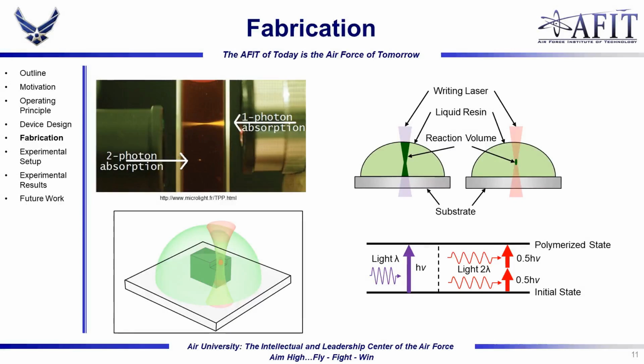Now, we've fabricated our device using two-photon polymerization. This is an additive manufacturing technique, similar to stereolithography 3D printing, in which a photoactive resin is selectively polymerized or solidified with a high-energy laser. Traditionally, this is done with UV light, but the same polymerization energy can be achieved with 2 photons at a higher wavelength. The volume within a laser beam that has sufficient energy for 2-photon polymerization is significantly smaller than the volume capable of single-photon polymerization.